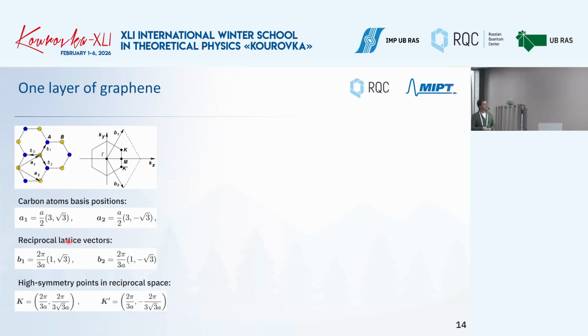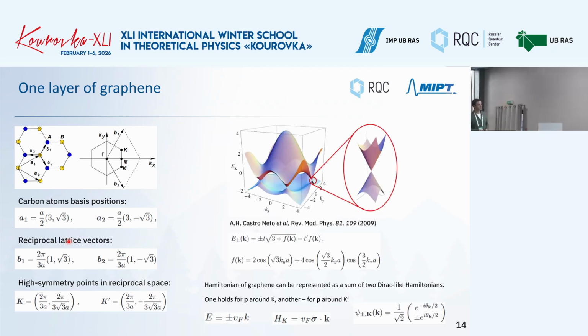Yeah, so in the single layer, monolayer graphene, you can describe it like this. This is the reciprocal space and the normal space. Reciprocal lattice here, so there are some values, and it's very well described, I think everyone knows, in the tight binding approach. From the tight binding approach, you can obtain this dependence. So basically you can describe the dispersion, and the dispersion looks like this. There are valence band and conduction band touching each other at one point, at the K and K prime points. Here are the K and K prime points, and then there is a linear dispersion around these low energies.